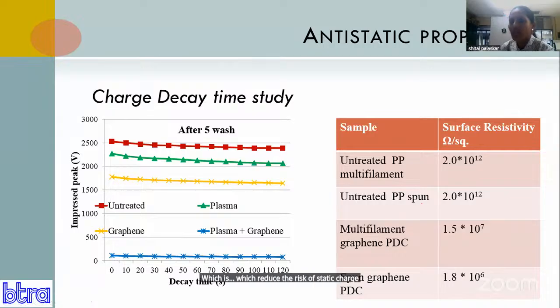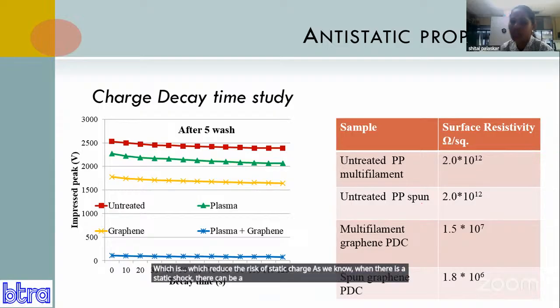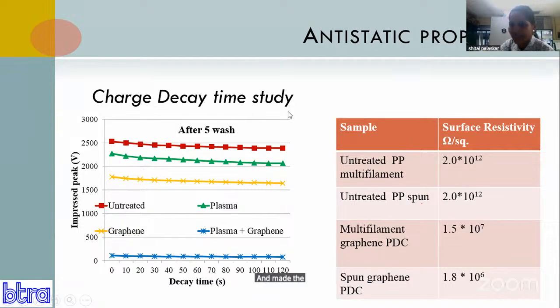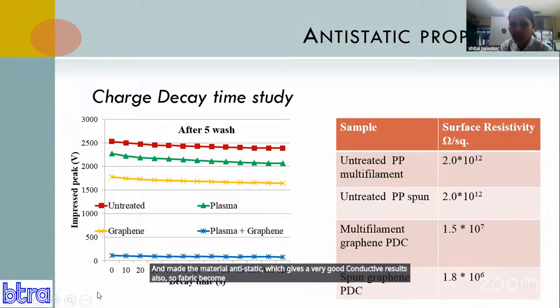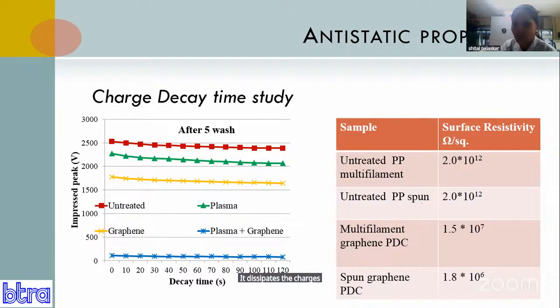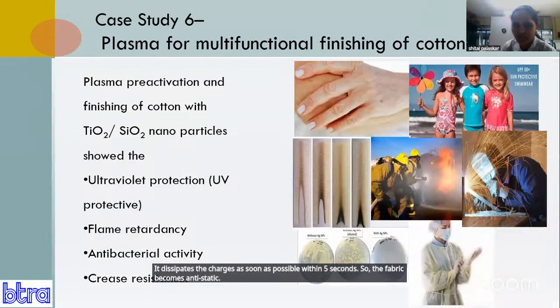And as we know, when there is a static charge, there can be a fire also. So we have mitigated all these causes using plasma technology and made the material anti-static, which gives very good conductive results also. The fabric becomes conductive, and it won't allow the static charge to stay on it. It dissipates the charges within 5 seconds. So the fabric becomes anti-static.